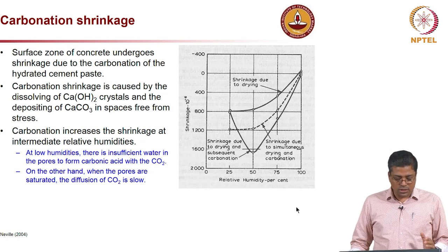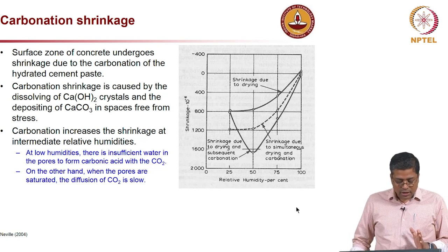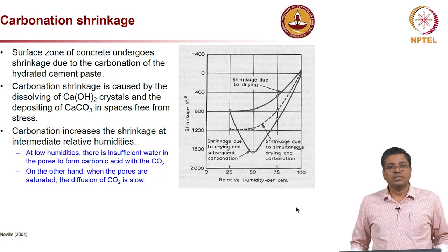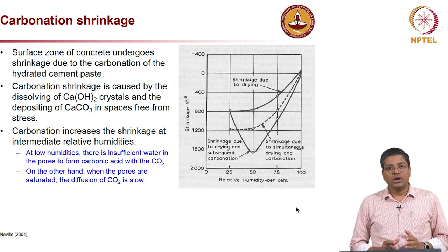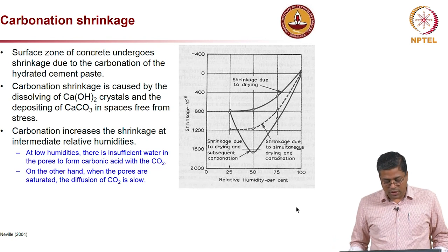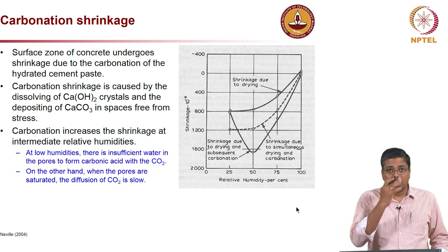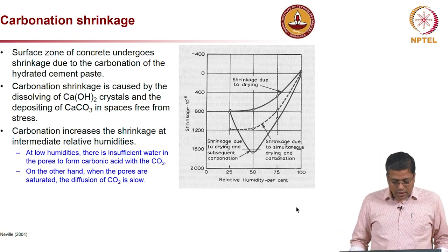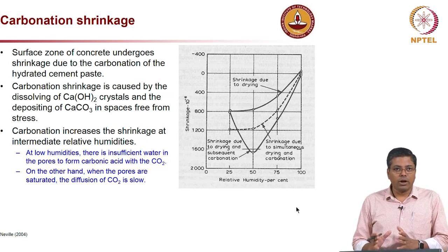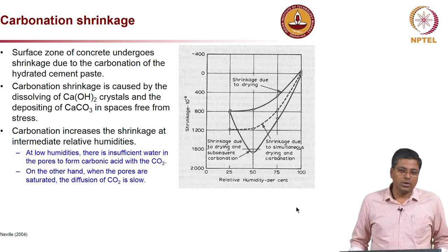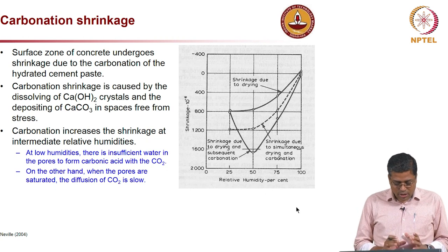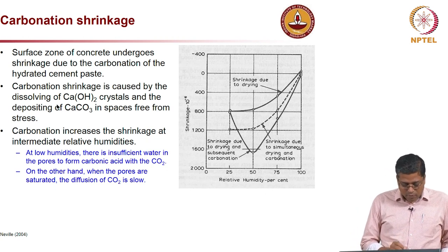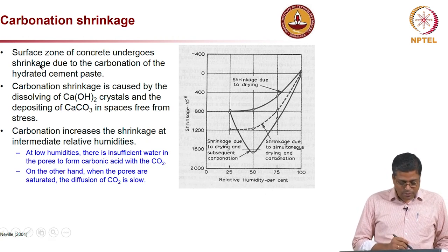Now, carbonation shrinkage is the last form of shrinkage we are going to discuss, and this is observed in some concretes in the very long run, because after a long time, when the concrete undergoes carbonation, it leads to products which have a smaller volume, or it leads to shrinkage. So, let us look at the mechanism.